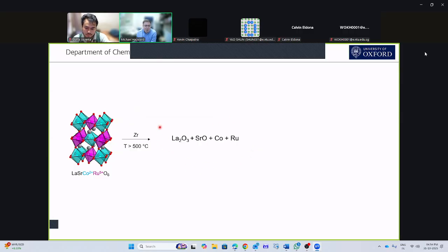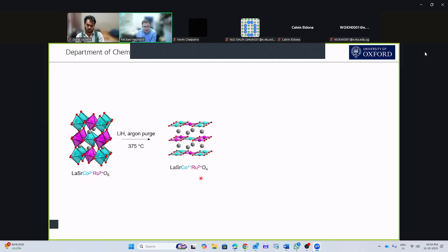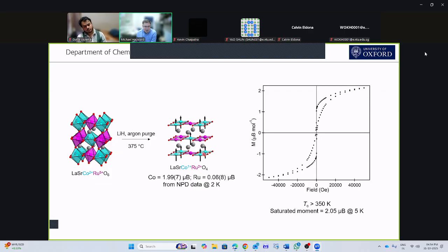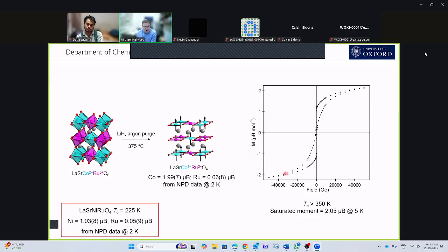Well, it turns out not with zirconium. The sample decomposes, but what we can do is if we treat this with lithium hydride, but now not in a sealed tube under flowing gas, I can make the O4 phase that we were trying to make. And we find that this is also a ferromagnet like the nickel example, but it has a higher ordering temperature, which is way above room temperature rather than below room temperature at 225.